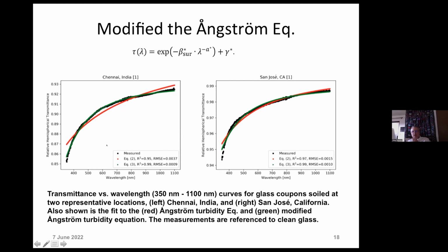What you should take away from this presentation, one of the things, is that for natural soiling in multiple locations across the planet, we always have this same general shape of low transmission in the blue region, and then slowly becoming higher transmission, never quite becoming one, but this depends upon the level of soiling, and this could be modeled by the modified Angstrom equation.